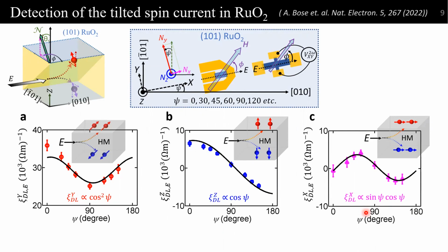Oh, okay. Another question is related to the device size. You measured these properties using ST-FMR and also second harmonic measurement. May I know what the device size is in both cases? For the ST-FMR, I think the size we had is 20 by 30 micrometer square, and for the second harmonic Hall, probably the length was 20 micron and width was 6 micron, but in that range. I don't remember exactly, but it should be in that range. Okay, thank you.